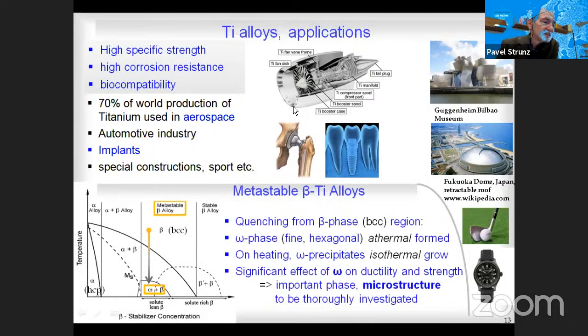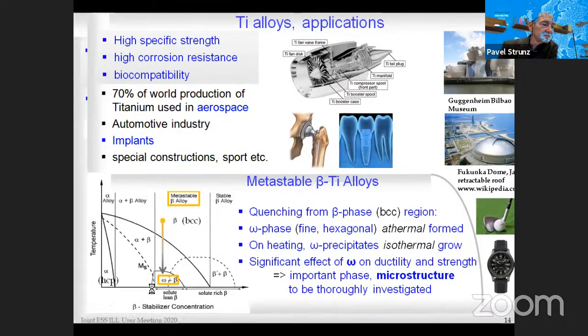A special class of these alloys are metastable beta titanium alloys, where during quenching from the beta phase region, a fine structure of hexagonal omega phase appears, and this can grow on further heating. Because it has a significant effect on ductility and strength, the precipitate microstructure of omega phase is worth investigating thoroughly.